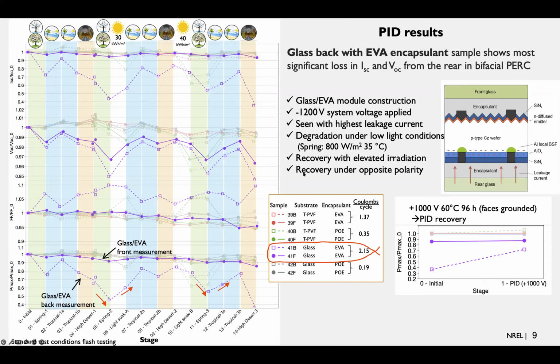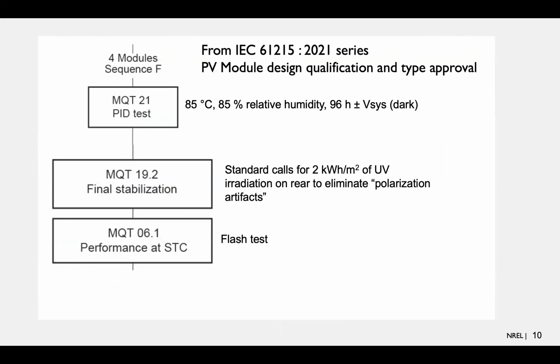So, with all these bullets here checked off, we make the conclusion that the glass back with EVA encapsulant module could be showing potential induced degradation in the polarization mode. So this has some implication for the standards.